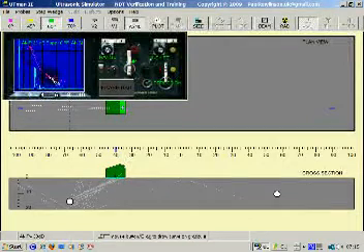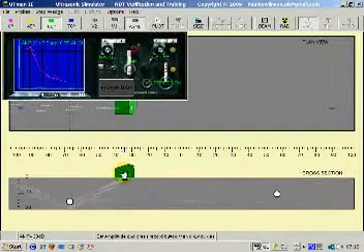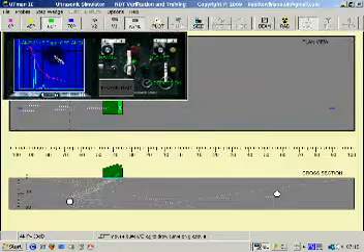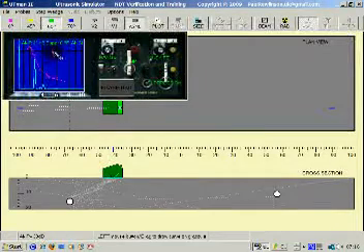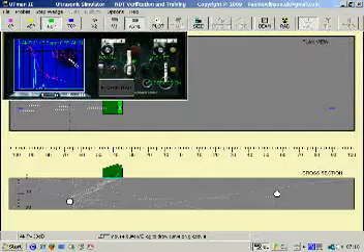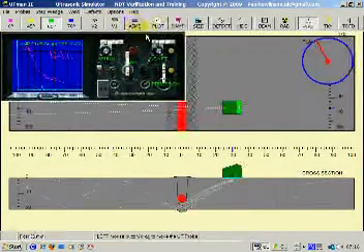This is called a DAC curve, and this represents the response from the same size holes based upon distance. Distance amplitude correction, DAC, distance amplitude correction curve. If we now go back to the weld,